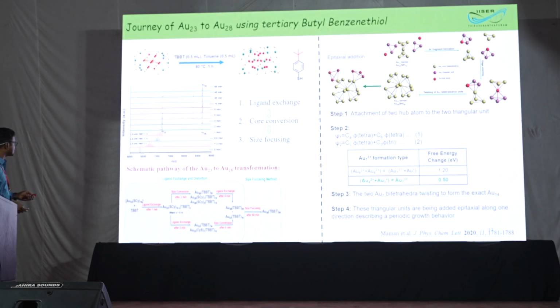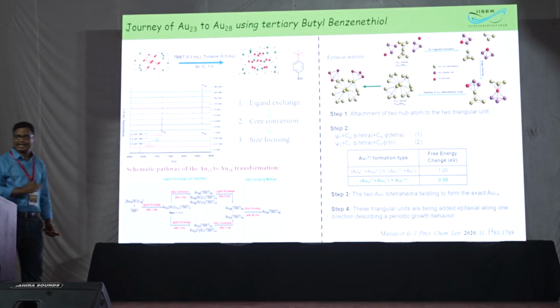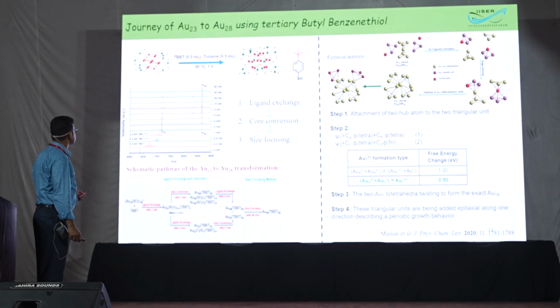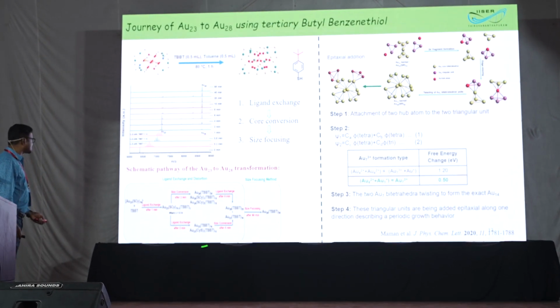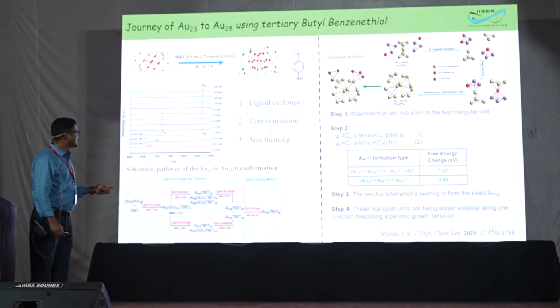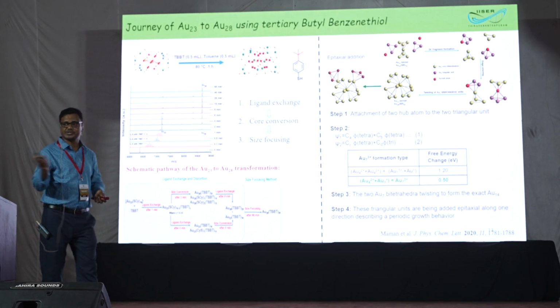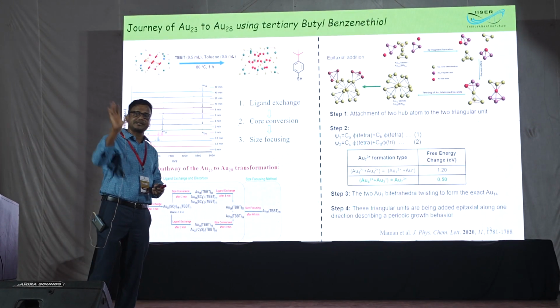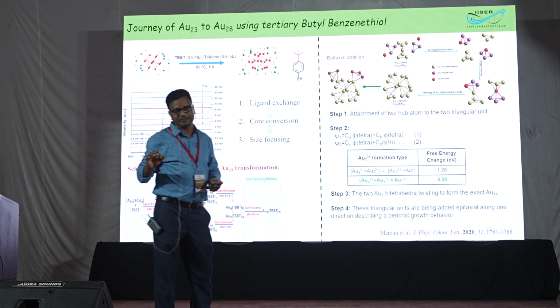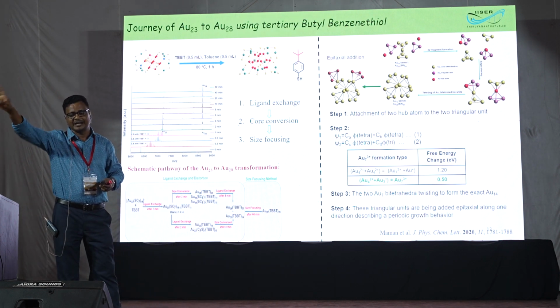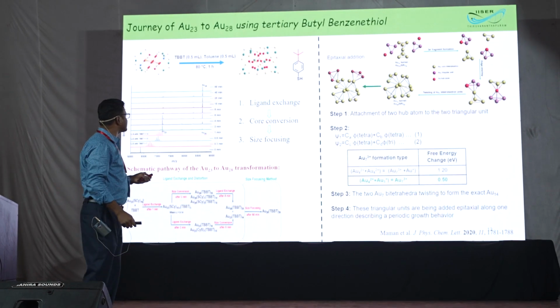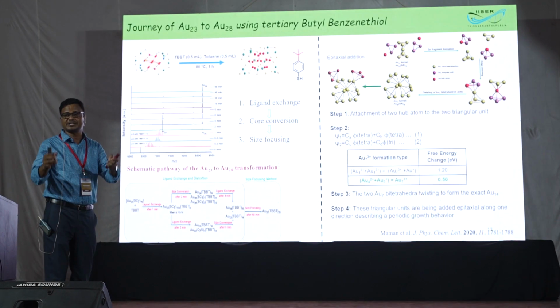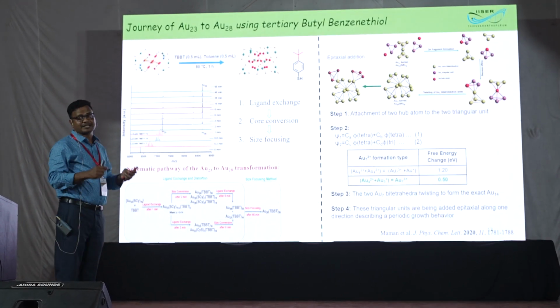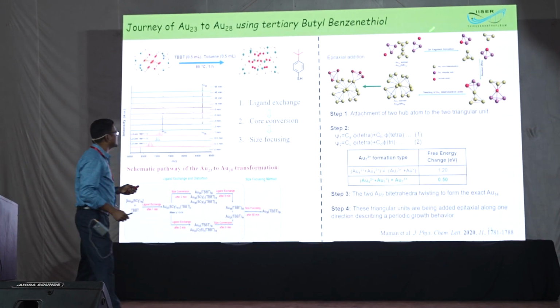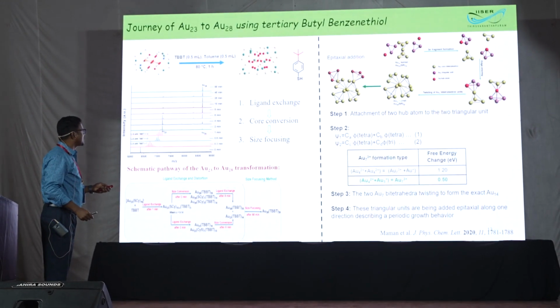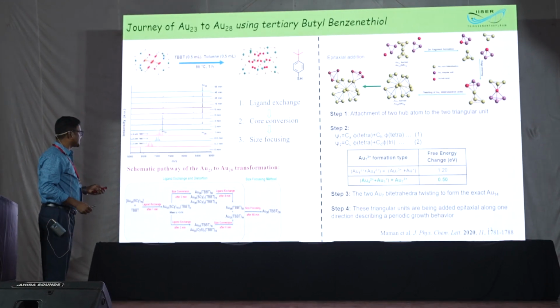Every 30 seconds, we stopped the reaction, purified the product, and analyzed all the products, and we can see that within 60 minutes, we are going to Au28. These are the intermediates we have isolated. Then you try to understand how things are happening. We did the calculation with Vishwarup Pathak at IIT Indore. They used our basic chemistry. We know molecular orbital theory, linear combination of atomic orbitals, and two-atom exchange coupling. So we have Au4 and Au3 units that we consider as cluster units. Then with exchange coupling, cluster orbital theory, we can see that these are the cluster units available in Au23, and this forms Au28, and if you keep on going, you will get Au36.